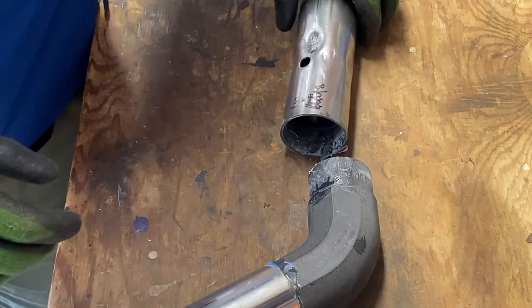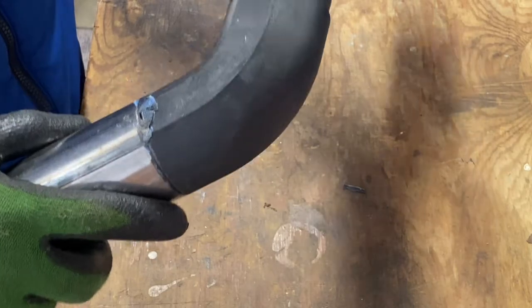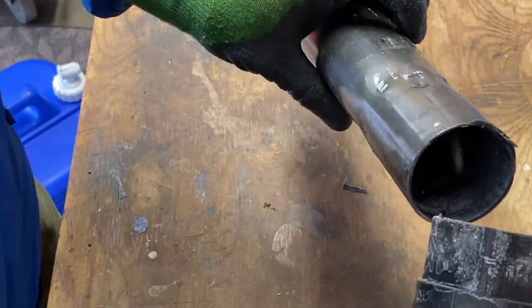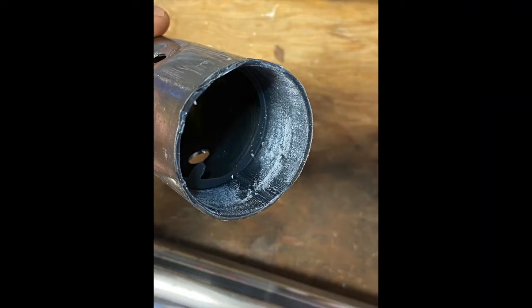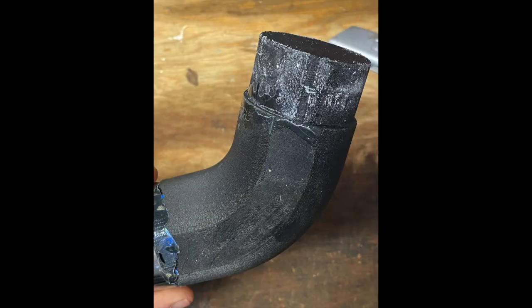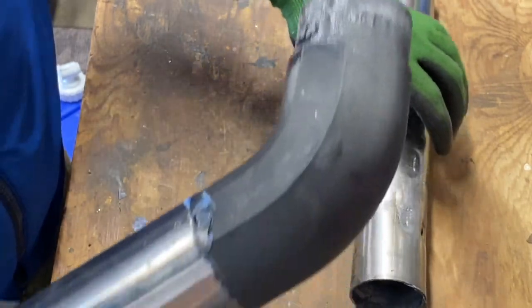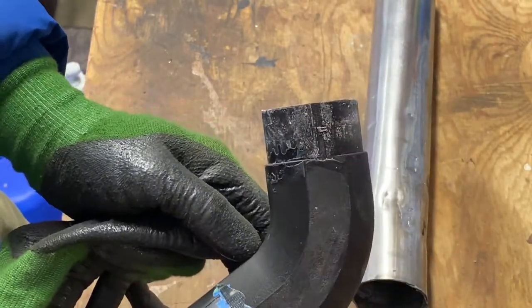Well, that was a process. I ended up having to stick this in the vise, which totally mangled up the tube, and eventually probably 50 times of reefing this back and forth to very slowly work its way out. It's interesting to look at — you can see how the epoxy kind of all pushed in there. It looks like it mostly stuck to the pipe and not so much to the lug, which I had heard this kind of epoxy maybe doesn't like nylon quite as much. But even so, that was a lot of force I had to put on this to get it apart — far beyond, I think, what it would see as a camera gimbal. As far as I can tell, this printed piece is entirely intact and undamaged.